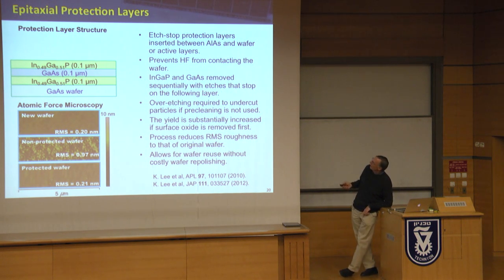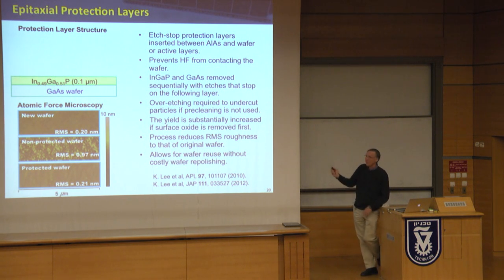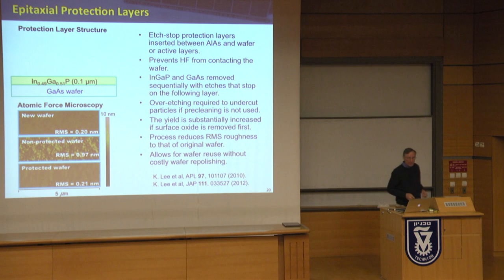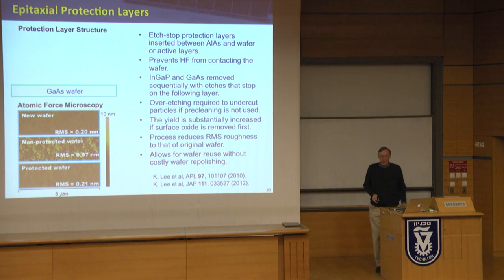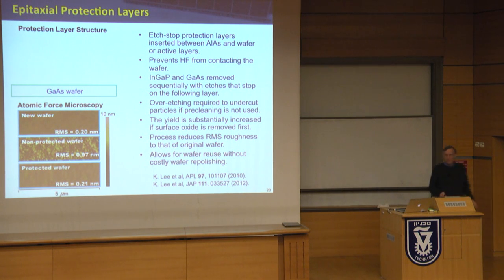Now it's fairly clean. And now we use a selective etch. Although this is maybe still slightly rough, it doesn't have the arsenic oxide on it anymore, so we can then etch this with a selective etchant and remove it right down to the gallium arsenide. And then we can use another selective etchant to move it down to there. Actually, we've gotten rid of the last indium gallium phosphide layer. And you can see that this is a fresh wafer from the vendor, and this is the protected wafer. It's absolutely pristine.